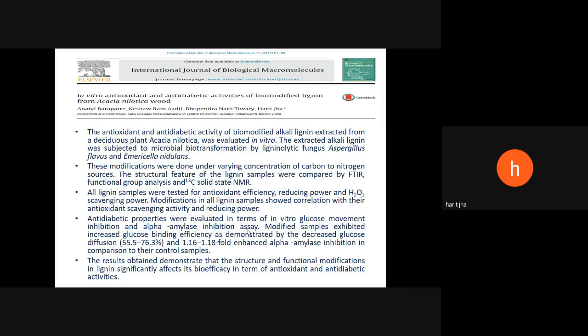In this, we tested after modification and before modification the antioxidant efficiency, reducing power, and hydrogen peroxide scavenging power. We also tested the in vitro anti-diabetic activity in terms of in vitro glucose movement inhibition and alpha amylase inhibition ability. We found that the structural and functional modification in lignin significantly affected its bioefficacy in terms of antioxidant and antidiabetic activity. That is, it improves the activity.